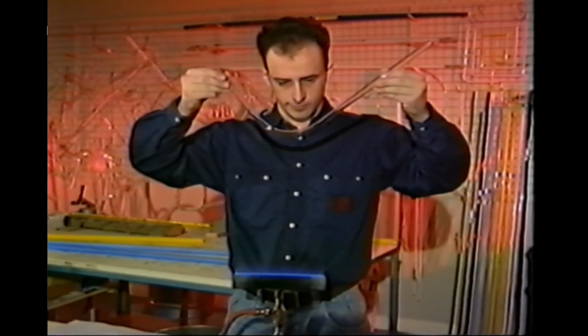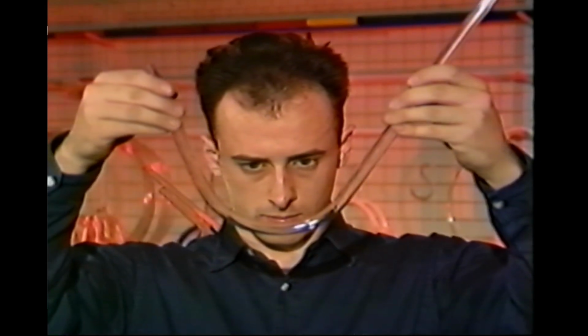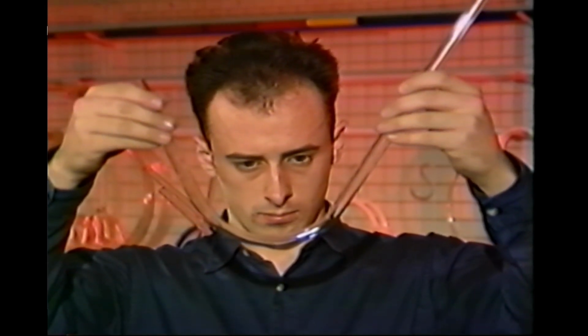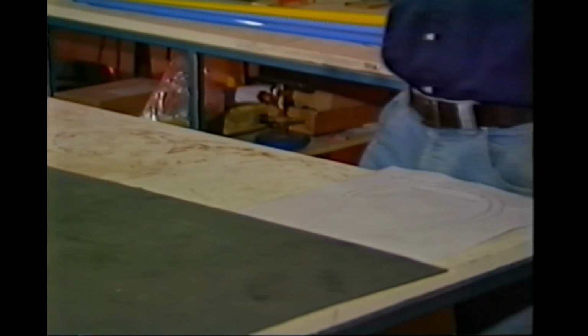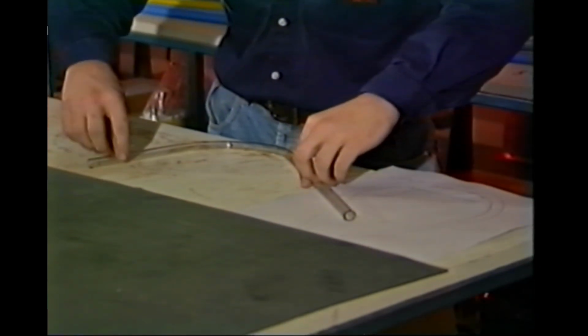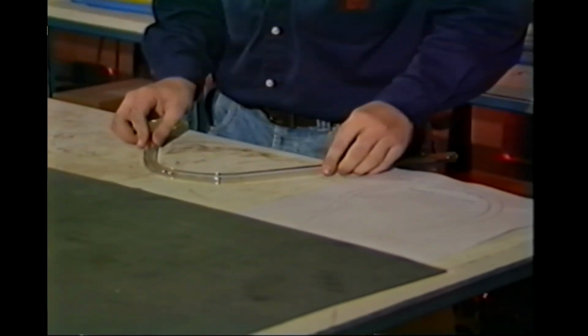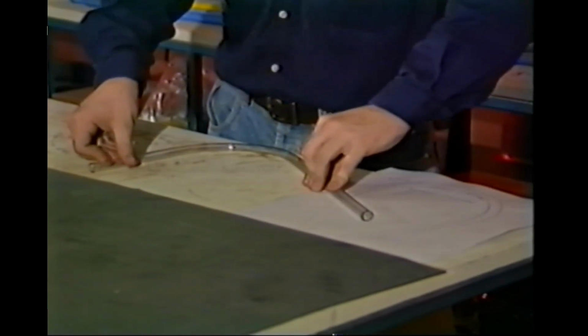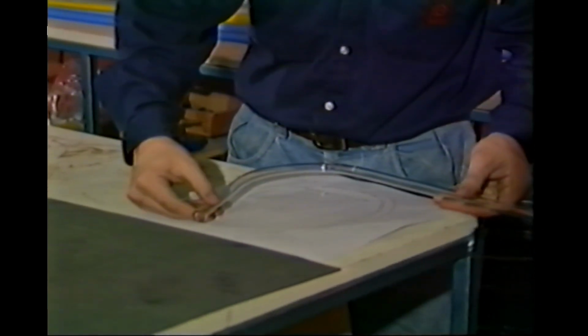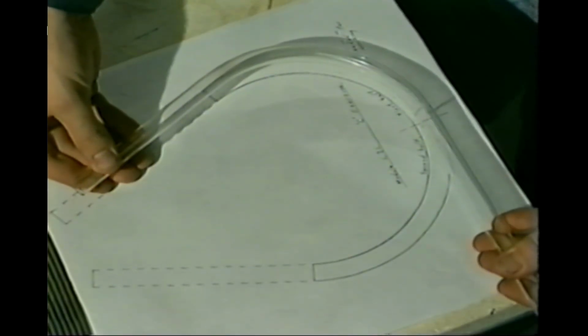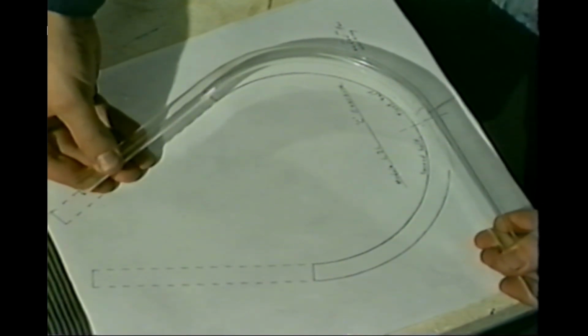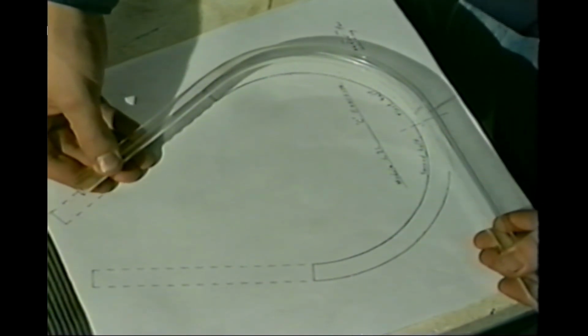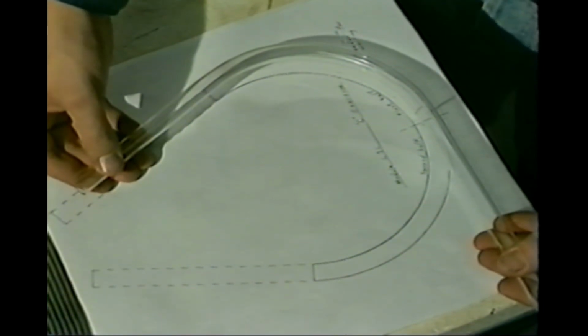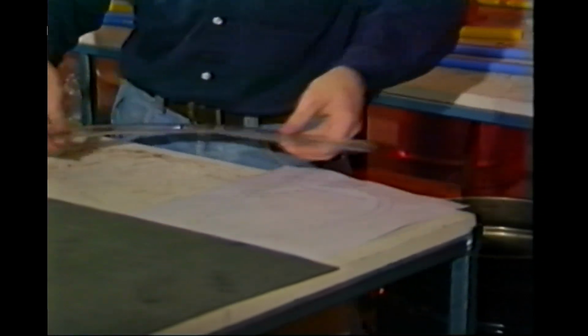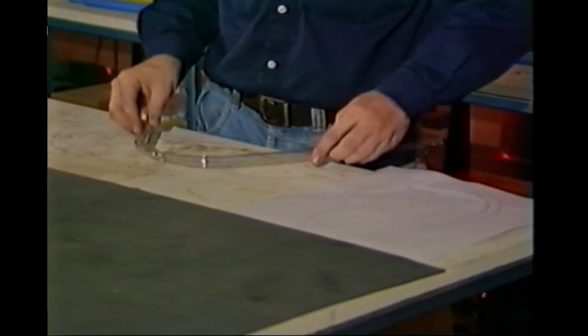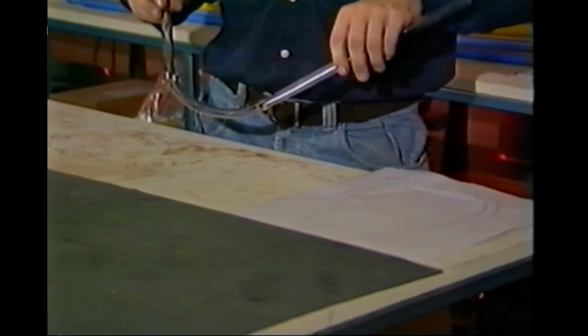Raise the tube up to eye level out of the flame and shape both hands out and up to produce an even curve, trying to judge the amount of curve by sight to enable easy fitting to the drawing. When the curve is complete, quickly lay it on the bench top to flatten it more quickly to the drawing. Line the center mark on the tube with the center line on the drawing, and while keeping the tube up off the drawing, adjust the curve to fit, followed quickly by flattening again on the bench top. Lift from the bench top quickly and leave to cool down.